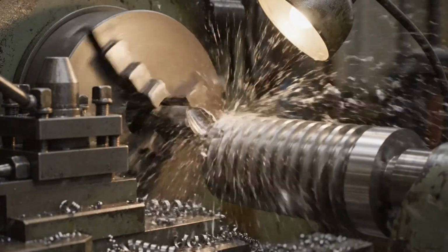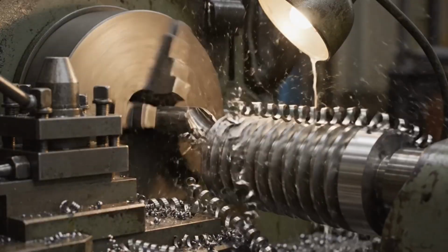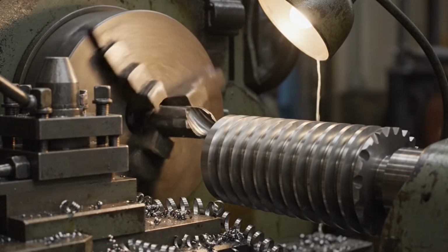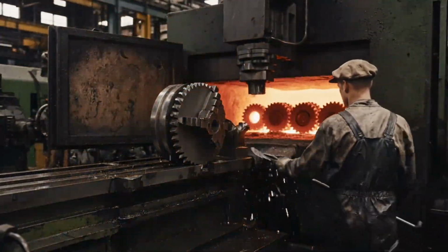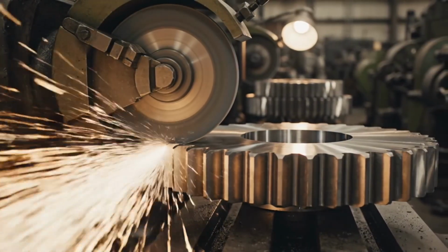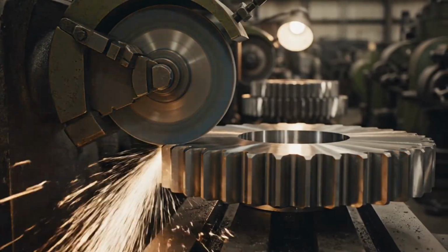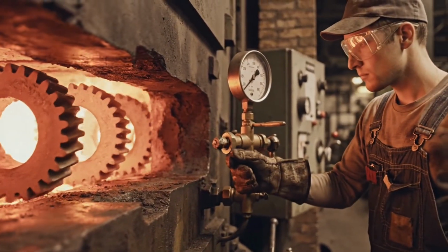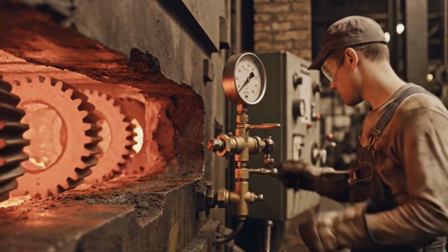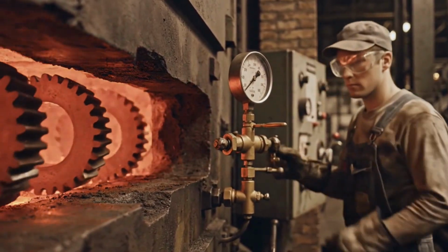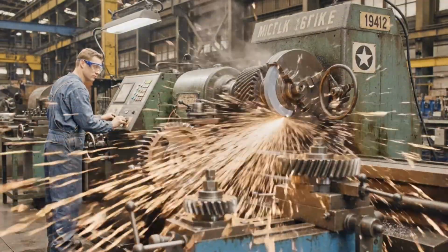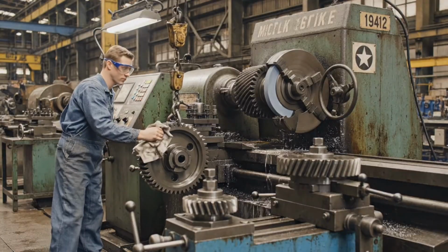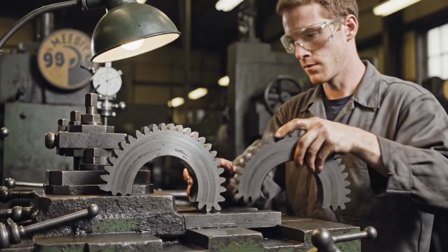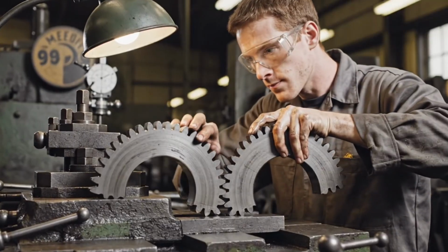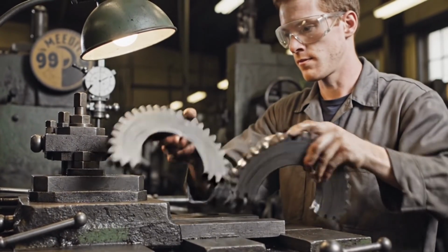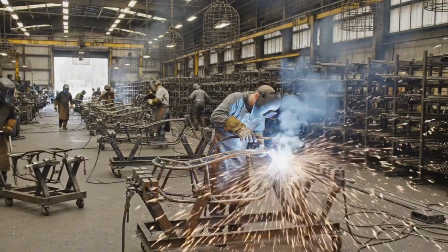Cutting these gears required hobbing machines, which used a rotating cutting tool called a hob that moved in precise synchronization with the gear blank, gradually shaping the tooth profiles into the metal over multiple passes. After hobbing, the gears were case-hardened through a heat treatment process that created a hard outer surface while leaving the interior of the gear tough and resistant to shock. They were then ground on a gear grinding machine to achieve the final tooth profile and surface finish required for smooth, quiet, long-lived operation. Each completed gear was tested for fit against its mating gear before it was approved for assembly.